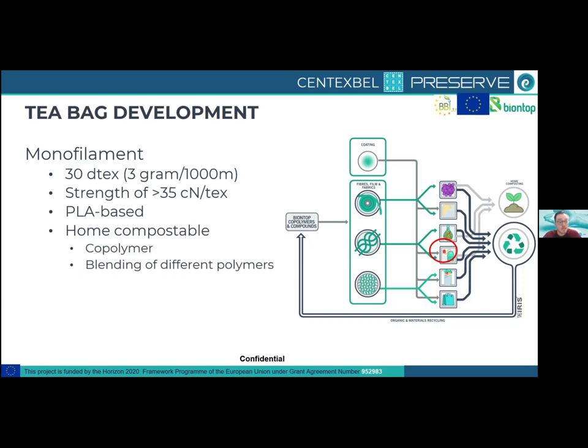difficulties. With hot water at 100 degrees, you need to be able to make this and still be strong at that temperature, but also the filaments themselves. This is a textile demonstrator where we make filaments that are very, very thin. So 30 dtex, which means 1000 meters of the filament weighs 3 grams. And it has a very high strength of over 35 centinewton per tex, which is a PLA-based filament.